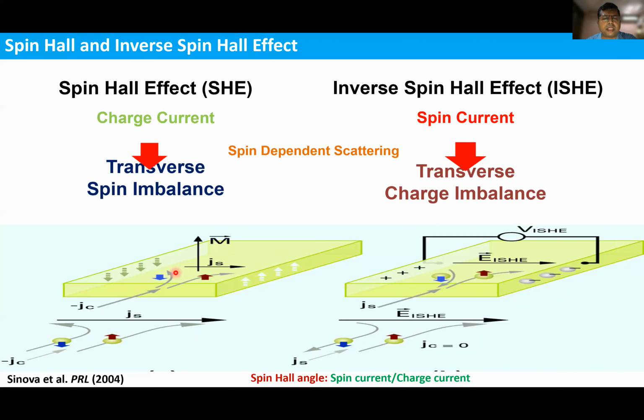However, it is very difficult to measure the spin Hall effect directly. You can do that by magneto-optics principle to measure the spin current, but it is not very straightforward. However, people discovered that you can just take the reciprocal of the spin Hall effect, which is known as the inverse spin Hall effect. Assuming you have already created a spin current, if you pass it through a high spin orbit coupling material, you will be able to generate the Hall voltage, and you can calculate the spin Hall angle, which is the ratio of spin to charge current, or vice versa. And we are looking for materials which can exhibit a high spin Hall angle for efficient charge to spin conversion.